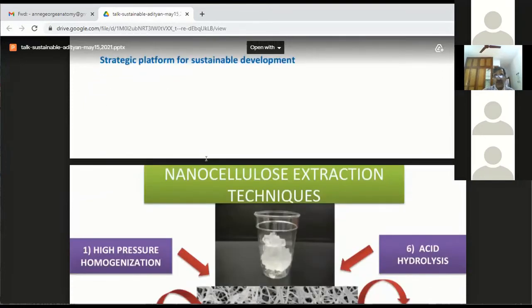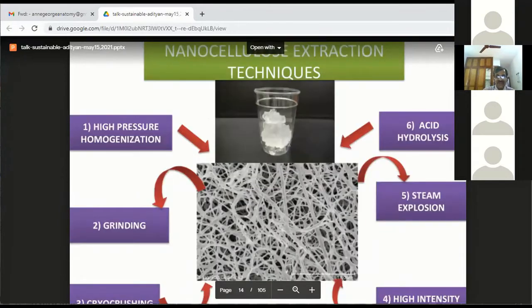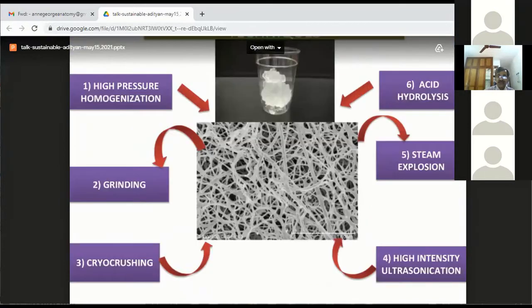Let me now show you the electron microscopic picture of nanocellulose. Look at this, this is the electron microscopic picture. If you examine nanocellulose under electron microscope, high resolution electron microscope, you will see like this. You have a continuous wave-like structure. And the diameter of this cellulose is something like 20-25 nanometers. And they're pretty long. It could be even micrometer long. And if you make nanocellulose and put it inside a transparent glass tumbler, you see this is nanocellulose gel, transparent gel. How do you make them?